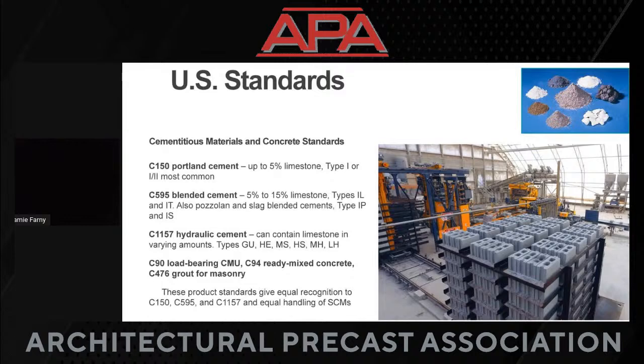So that's spelled out in the standard. Any material that we're manufacturing that's called a PLC or a type 1L has to have limestone in between that range. We have some other cements in that standard. They're pozzolan and slag materials. So pozzolans are like fly ashes, and there's natural pozzolans too. Fly ash comes from the power industry. When we burn coal, we catch what goes up the smokestack, and it actually is a really good addition to cement and concrete. So we have these type 1P and 1S materials, but we also can have a third or a fourth cement, a type 1T, and it allows for the addition of limestone and/or pozzolan and/or slag. So we have to have clinker in there.